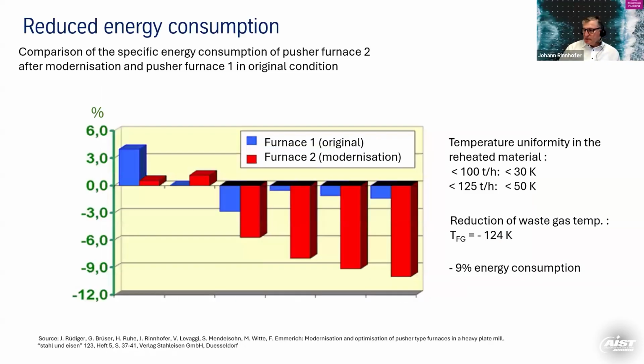The end result is we have reduced energy consumption of the furnace. The modernized furnace is showing here, the red columns. So we have an energy consumption reduced by 9% in comparison to the original situation, and also to furnace number 2, which is sitting next to furnace number 1. So, 9% energy consumption, we have a reduction of the waste gas temperature of minus 124 kelvin.